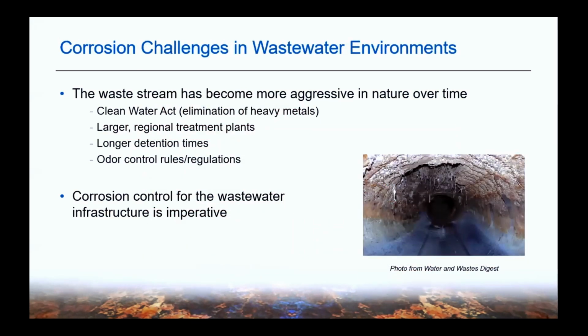So when we talk about corrosion, it's important to talk about corrosion specifically in water and wastewater, and how did we get to where we are today? The fact is the waste stream has become more aggressive in nature over time. It was fairly common 30 years ago to find hydrogen sulfide concentrations around 10 to 15 parts per million. However, with such things as the Clean Water Act, which eliminated heavy metals from the waste stream, we've seen those numbers increase exponentially, which in turn has caused a lot more corrosion.